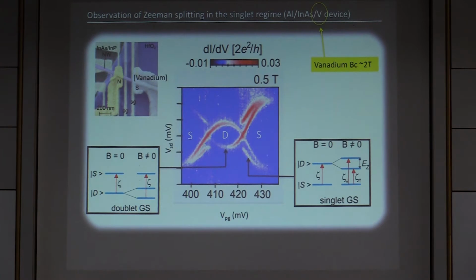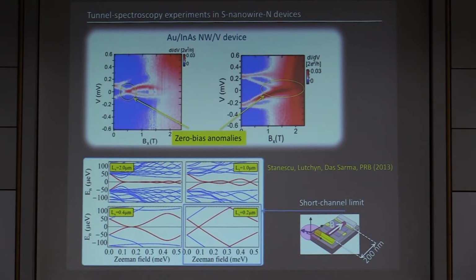Now, in an earlier experiment, we also investigated the effect of the magnetic field. If you apply a magnetic field, you will see that if you sit in the singlet state, then you can resolve these two transitions. And so the Andreev state splits due to the Zeeman effect. And as it was also shown this morning, this splitting of the Andreev levels can result in the emergence of some zero bias anomaly, as shown over here, because two of the Andreev states basically go together and meet at zero energy.